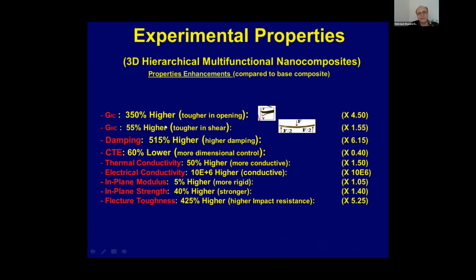So we improve the property in many different areas like fracture toughness, mode 1, mode 2, damping, coefficient of thermal expansion, thermal conductivity, electrical conductivity, in-plane modulus, strength and toughness. You see all of them improve like 4 times, 6 times in different areas. For example, fracture toughness improves 4.5 times, damping 6 times, thermal conductivity is 1.5, and then huge thermal conductivity. Huge electrical conductivity because through the thickness, epoxy is not conductive. We put in carbon nanotube, it becomes conductive. Again, flexure modulus, the strength and also flexure toughness improve.